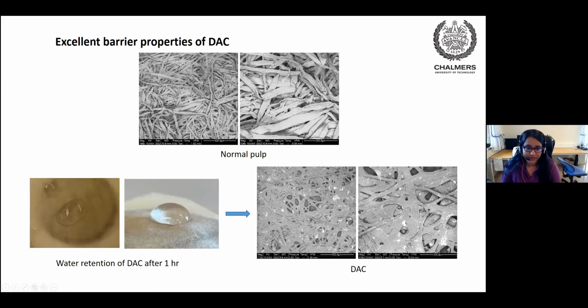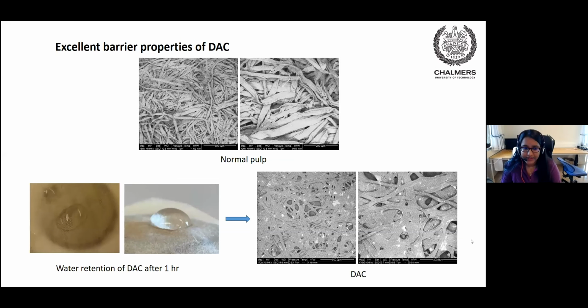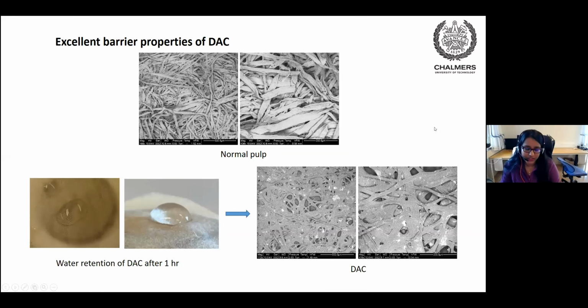Now, as I mentioned, dialdehyde cellulose seems to have excellent barrier properties. It is quite evident in the slide. In the picture at the top, we see normal cellulose pulp, with fibrils of cellulose strands stacked one upon another in a very haphazard manner. After oxidation, we produce the dialdehyde cellulose, which, as I previously mentioned, has good barrier properties, and you can see that from the picture on the left-hand side.